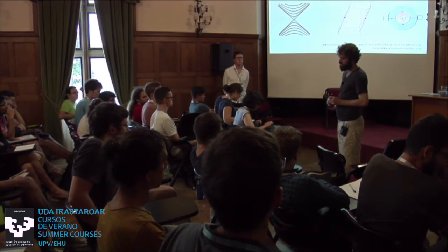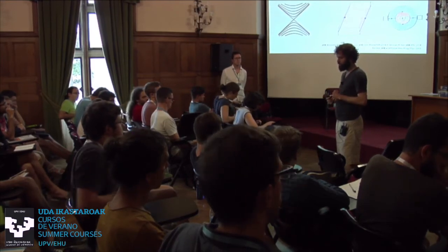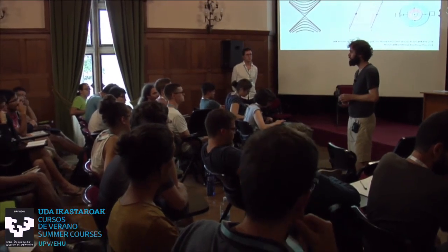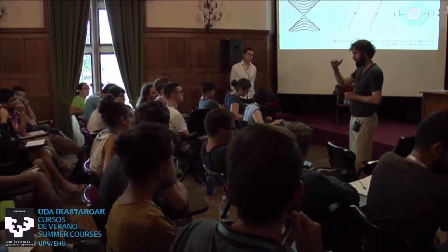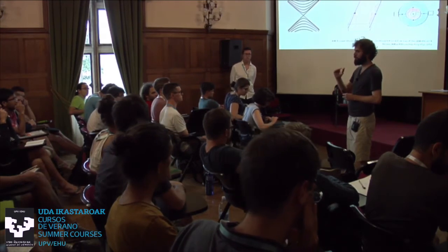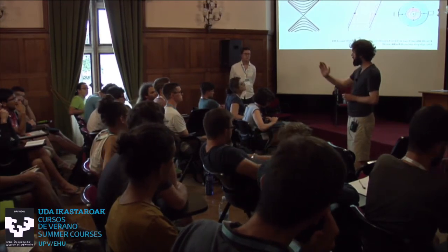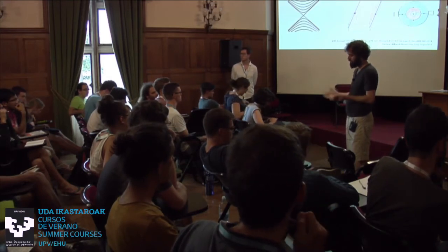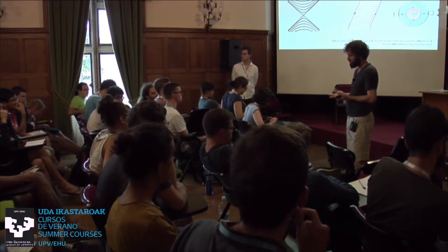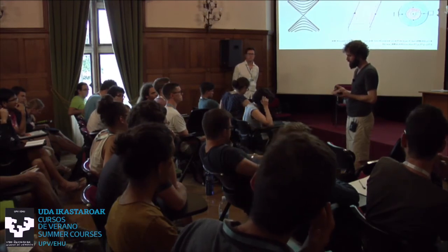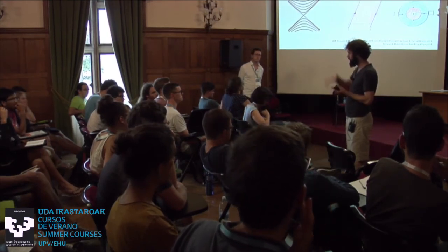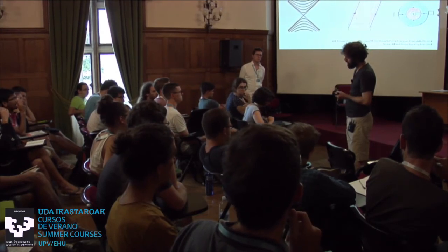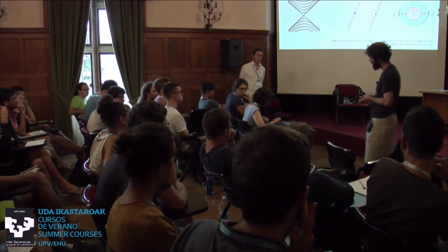And the main reason, if you wanted to go to the regime where you could see Majorana physics, then you need to reduce the number of modes such that the signatures of the Majorana mode dominate your signal. But in most materials, making these wires, it's hard to control the growth such that you can tune the chemical potential to be very close to the Dirac point.